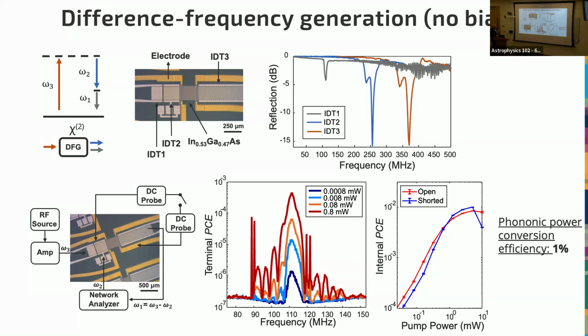In this case, because we're using this very long wavelength acoustic wave at 100 megahertz, it has a significantly slower wave speed than the two higher frequency waves, which only see the lithium niobate. This one has a much longer wavelength, so the frequency is lower, and it's interacting more heavily with that silicon substrate, and that ruined the phase matching basically. And so we only got about 1% conversion efficiency here, but again, with optimal phase matching in this system, we could easily get this back up to be as good as the sum frequency generation.